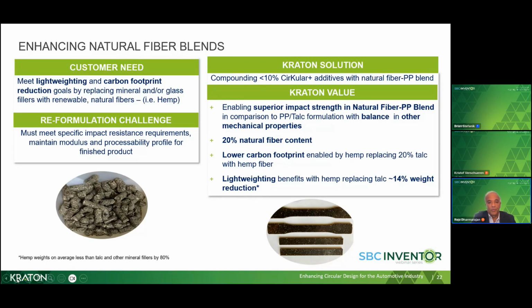So using our Circular Plus modifier, we are able to maintain the balance of impact and flow and stiffness, as you saw in the previous slide. And we achieve properties that are comparable to the polypropylene talc formulation. So we have replaced talc with 20% natural fiber. So we see that big reduction in carbon footprint with the hemp replacing talc. And at the same time, because, as I had mentioned previously, hemp is a much lighter material, we are also able to lightweight the product and get a 14% weight reduction.